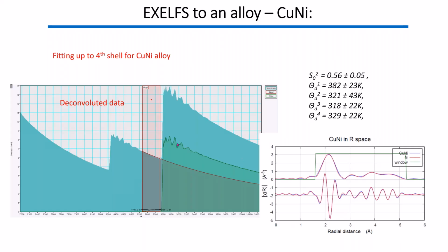And the reason we chose copper for fitting is just because copper first has more oscillation, and also its tail doesn't have any further edge to go, so that's a bit cleaner. And of course, you can also choose the nickel K edge to do the fitting as well. That's not a big problem.